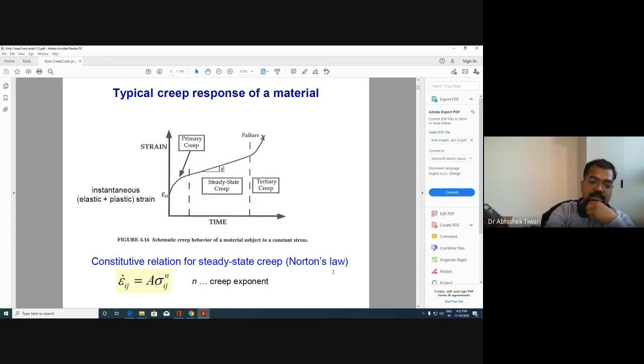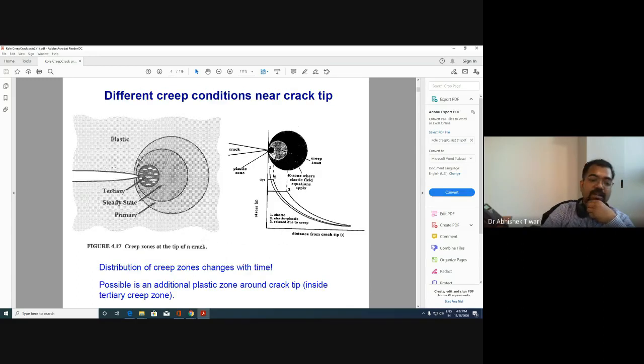So this describes the creep behavior, but once you have a crack in the system, then as we have seen, you will have a plastic zone in elastic plastic deformation. Similarly, in creep deformation, you will have a creep zone, okay? And as we have seen, the strain responds with time, and changes with the stress.